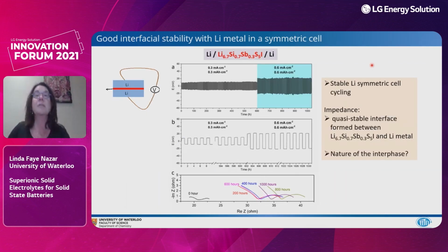I might just add that this material has pretty good cycling. It's not outstanding, but it's really not bad with lithium. This is symmetric cells with this argyrodite in between. And you can see that there's sort of a quasi-stable interface formed between this and lithium metal. And we're able to sustain modest current densities of 0.6 milliamps per square centimeter for upwards of 1,000 hours. And most importantly, you can see that although impedance increases modestly up to about 30 ohms, it's pretty stable over this cycling duration. And we still don't really understand the nature of the interface.